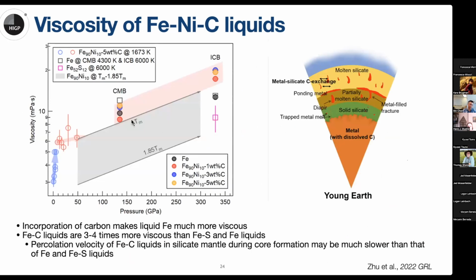So we also performed first principle molecular dynamic simulation to calculate the viscosity of this iron nickel carbon liquid at core mantle boundary pressure and inner core boundary pressure and temperature. We found that the viscosity increases from the CMB to ICB. And we also find that with increasing carbon content, the viscosity would be higher.